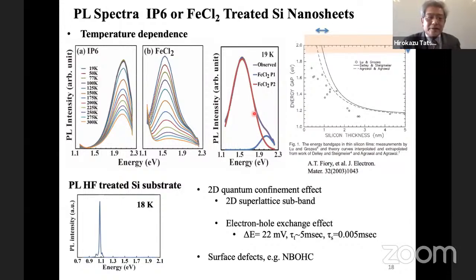So this is a photoluminescence spectrum of the nanosheet bundles. This is the expected or experimental energy gap for silicon nanosheet thin layers in the literature. Our material has a 1 nanometer thickness and has about a 2 electron volt energy gap. So we observe this luminescence at nearly 2 electron volts.